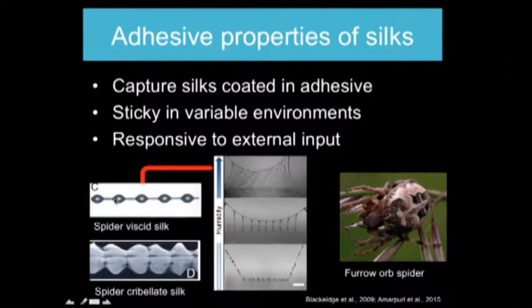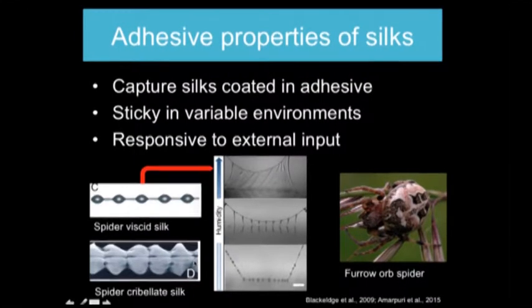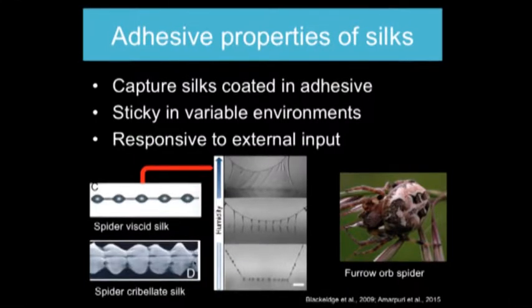But it's also, in the case of capture threads, very sticky. Now these are the spirals in the orb web and the fishing lines that I'll talk about later in the glowworms. They have similar properties, but these capture threads are coated in an adhesive. And in the case of viscid silk, like in many orb webs you see, it's a glue. It's an aqueous glue that coats along the thread, and they form into these droplets due to Rayleigh instability.